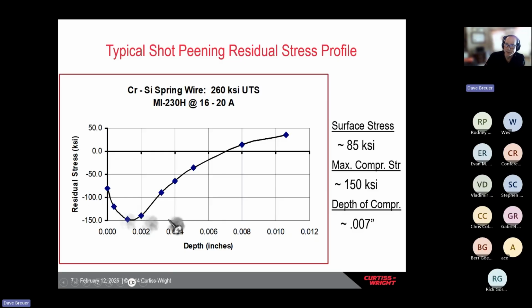Some of these variables are fairly predictable. The peak compressive stress from shot peening is usually about 1 or 2 thousandths below the surface, about 55% of the tensile strength. This spring has a tensile strength of 260 KSI, so 55% of that is about 150 KSI.